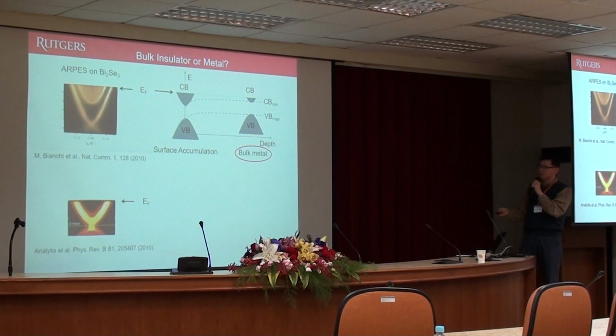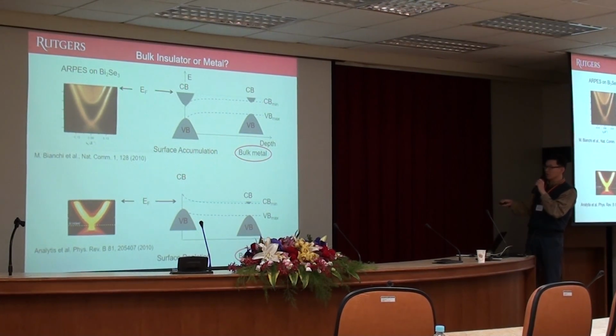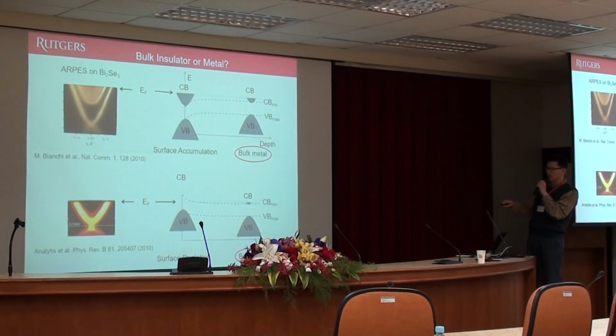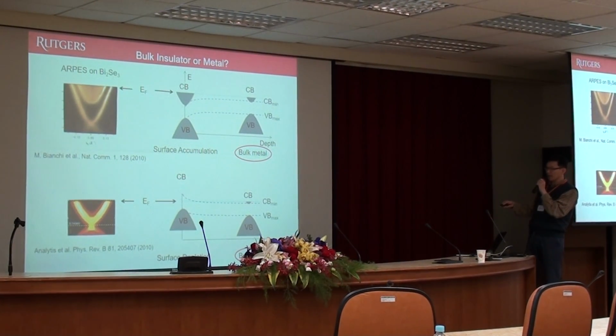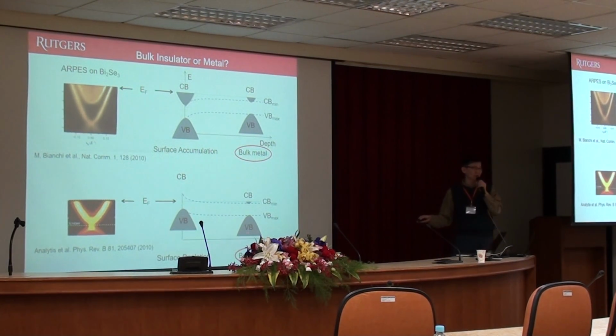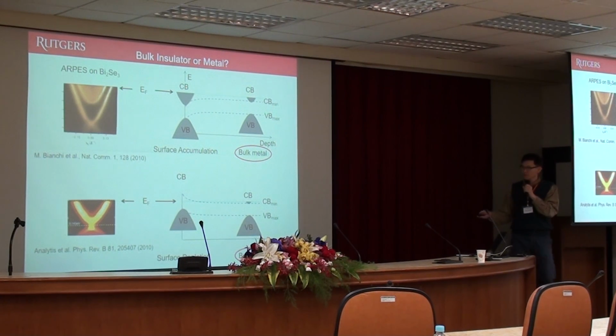But in fact, the reality is not that. Inside there's a band bending, and inside it is metallic over here. So it is not any surprise. But the surprise is, even in this case, people thought the Fermi level is inside the gap, but inside the bulk the Fermi level is still near the bottom, but still above the conduction band. So it was still metallic. Regardless of whatever you see in ARPES, bulk was always metallic. This turns out to be always the case.